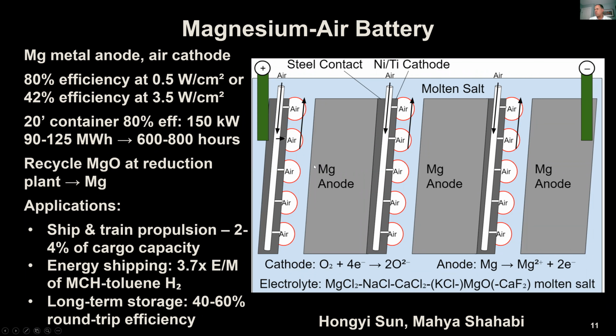So the battery begins with a magnesium metal anode and a porous metal cathode, which delivers air into the cell. Magnesium from the anode and oxygen from the cathode become magnesium oxide dissolved in the molten salt. So that's the overall reaction of the battery, magnesium plus oxygen to magnesium oxide. Many of these can easily be stacked in series as shown here for efficiency. The salt eutectic temperature and magnesium melting point bound the operating temperature between about 420 and 620 degrees Celsius.